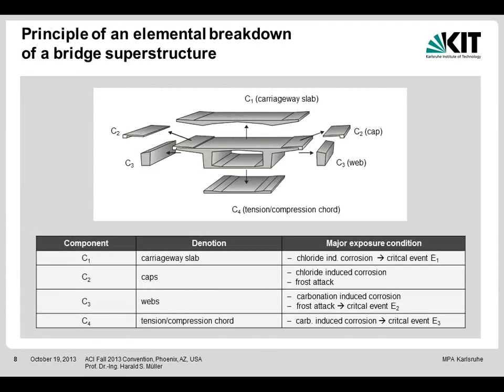And if we look, for example, at a structure, such as the superstructure of a bridge, we have to make an element breakdown, which can be rather simple. And we have to assign to the individual components, the carriageway slab, the caps, the webs, and the tension and the compression chord, the major exposure conditions, and we have to define the critical ones. For example, the critical one for the carriageway slab is chloride-induced corrosion.